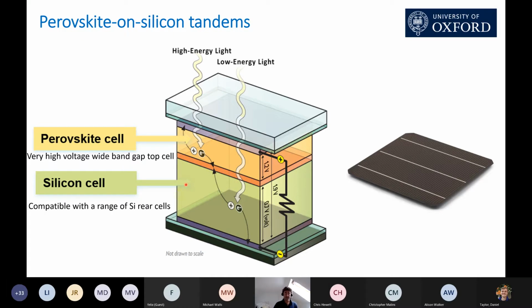And the efficiency of these cells is maximized when they absorb and generate exactly the same amount of current. Electronically, these cells are in series, and the current in a series circuit obviously has to be the same. So you want to generate the same current in the top cell and the bottom cell. That means we can tune the composition of the perovskite to get exactly the right band gap, match it with silicon. And the advantage of perovskites, and it's something that makes them almost unique amongst thin film materials, is that you can generate very high voltage from wide band gap materials. And that's what's needed. So here we get up to 1.2 volts or even beyond for the perovskite top cell, whereas you're only getting 0.7 volts addition from the silicon cell. And this ability to generate a high voltage with a wide band gap is what's really enabled perovskites to be very useful in tandem devices.